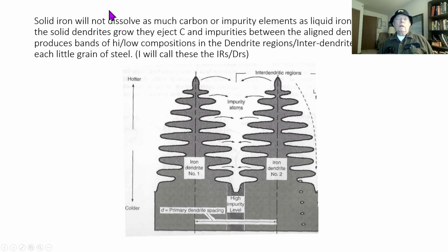Hence, as the solid dendrites grow, they eject the carbon and the impurity elements into the interdendritic regions, right here, here, and here. So you end up with interdendritic regions, which are high in impurity levels, and dendrite regions. We call this the primary dendrite spacing.